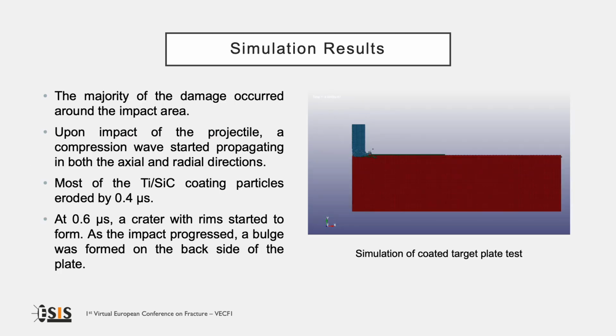The results of the simulation are reported in this slide. The Lexan projectile is completely destroyed during the impact, while the damage on the target is localized in the impact region. Upon impact of the projectile, a compression wave starts propagating in both the axial and radial direction. At 0.4 microseconds, most of the titanium silicon carbide coating particles are eroded. At 0.6 microseconds, a crater starts to form. As the impact progresses, a bulge is forming on the backside of the target.